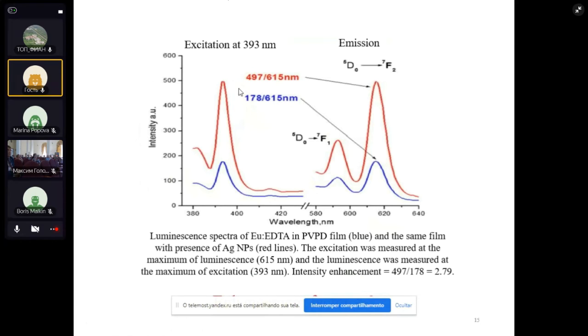And when we excite at the 5L6 level, they detected an enhancement factor of approximately 2.79. And notice that again, independently of the transition, the enhancement factor is the same. So it means, again, I would repeat this, it's the population of the emitting level of the europium ion which is being changed, which is being enhanced due to the presence of the metallic nanoparticle.